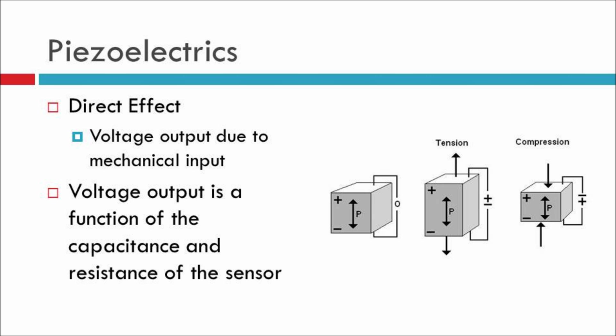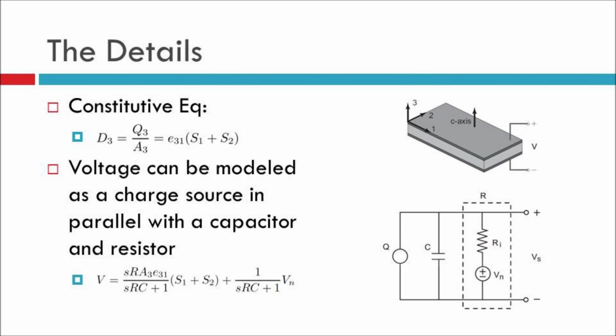For this application, I'm going to be using direct effect piezoelectric, which just means we're going to be measuring a voltage output that is due to a mechanical input. With piezoelectrics, the voltage output can be modeled as a function of the piezoelectric's capacitance and resistance. In an attempt to explain the voltage modeling in a little more detail, I've chosen a constitutive equation for in-plane stress or strains induced from the substrate, where S1 plus S2 is the transfer function from strain input and essentially acts as a high-pass filter, which actually becomes pretty important to reduce the noise from changes in temperature.